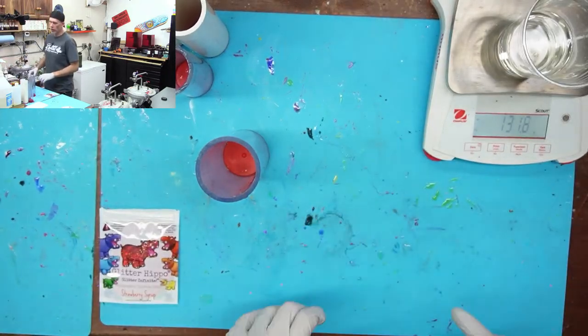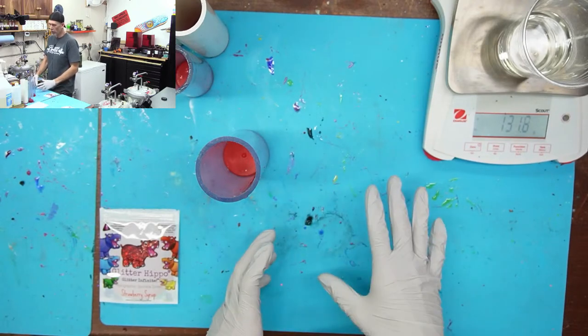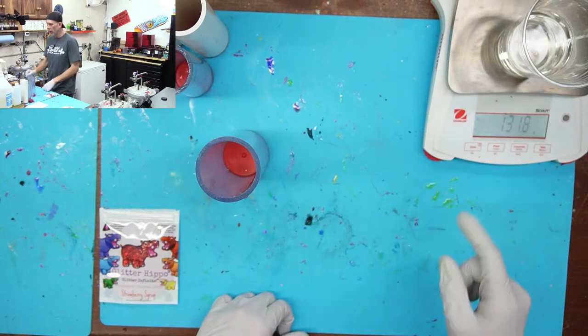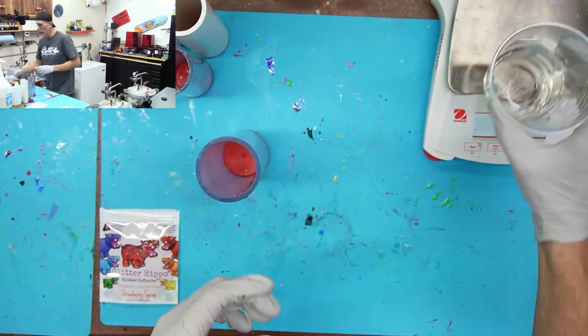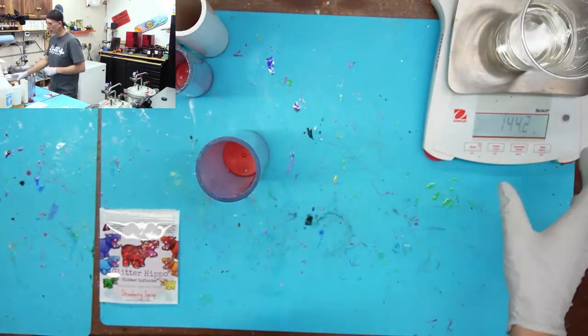Just be advised though, there's a lot of resins that sound the same. So Alumilite Clear Slow or just Alumilite Clear, those are both by weight. Amazing Clear Cast, which sounds kind of similar, that's totally different. That's an epoxy, and that one you need to do by volume. Okay, so weight is not going to work.